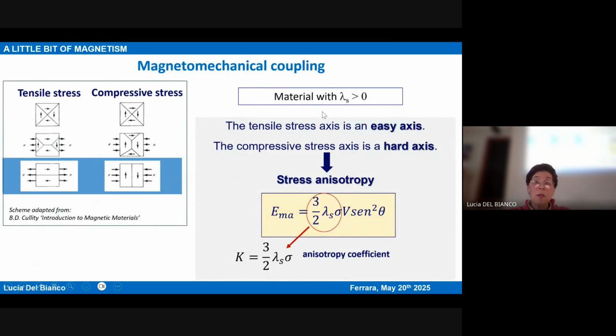And one of these consequences is this: if you have a material with positive magnetostriction and you have your ferromagnet subdivided into domains, and you apply a tensile stress, as shown here, then the direction in which you apply the tensile stress becomes an easy magnetization axis, an easy anisotropy axis. And on the reverse, if you compress your sample, the compressive stress is a hard axis. And this means that by applying an external stress, you give rise to a form of anisotropy, which is called stress anisotropy or magnetoelastic anisotropy. And it is given by this expression, namely, the anisotropy coefficient K is proportional to the saturation magnetostriction and to the stress. Okay? This phenomenology is called magnetomechanical coupling.